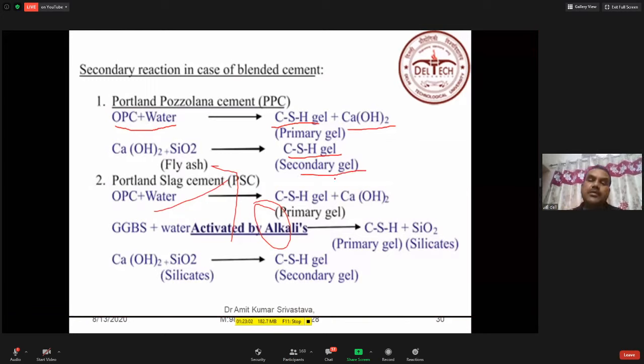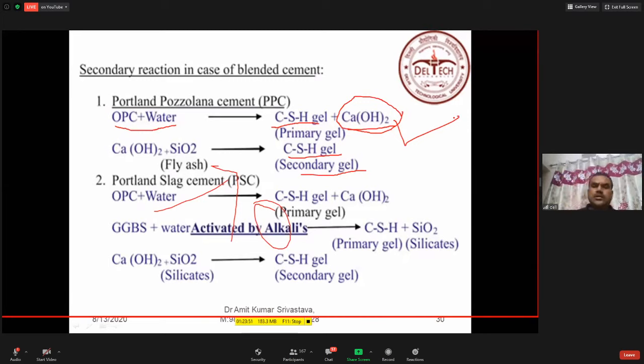So what happened? Whatever free lime is available, if you are using fly ash, it is creating more CSH gel, and more CSH gel means what? You are getting better concrete in terms of strength and durability. Because this calcium hydroxide, if it is not used and is left, will cause carbonation of the concrete, corrosion, and lots of problems. So if I am using OPC only, then these leftover products are very dangerous for the life of the structures. If I am using fly ash, this dangerous material, calcium hydroxide, I am utilizing fully. And once I utilize it fully, it is not available for carbonation and creating durability effects to the concrete and corrosion to the reinforcements.